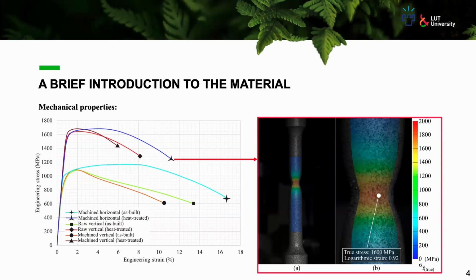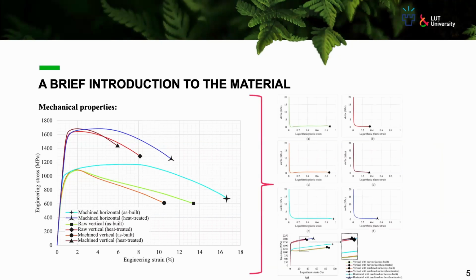So the combination of ductility and high strength is a perfect combination for many mechanical applications. And of course, we have the strain hardening aspects of this material as its major properties. In the as-built situation, we can detect a recovery stage in this material, which is not present in the heat-treated version.